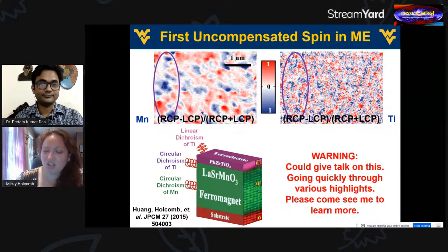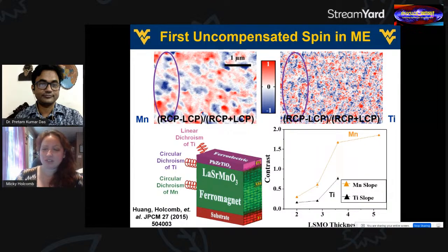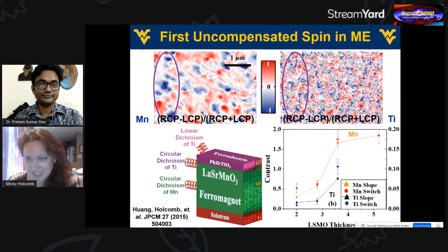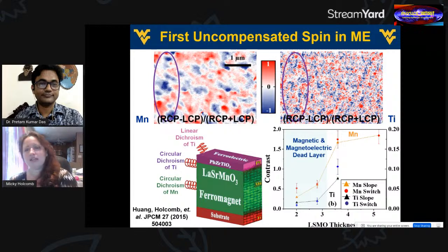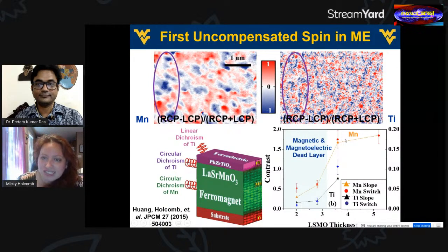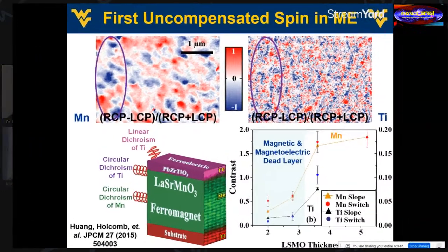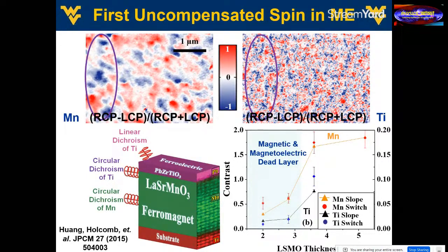But we actually learned a lot from this. So we were able to develop two different techniques on the left and right side of this graph, which gave us essentially similar answers that showed us a couple of important things. One, it showed us that our contrast, our intensity, went down for our magnetic layer when the magnet got thin. This is an effect I'm going to focus a lot on here soon. And in that same space, when the magnetism starts to die off, the effect that we got from the interface also died off.